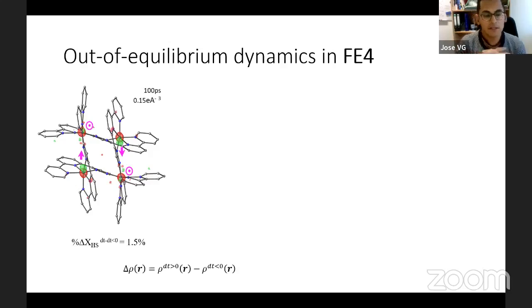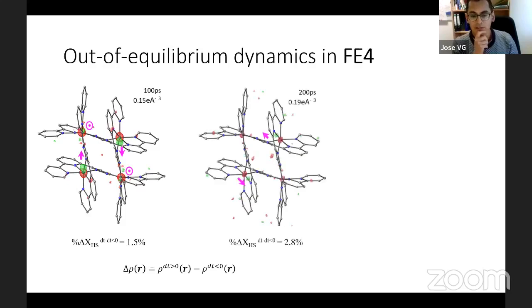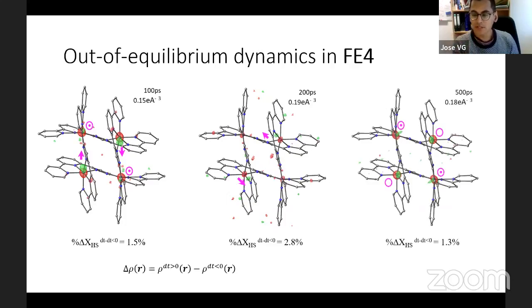And as you can see in the figure, I have put some pink arrows showing more or less how the electron density is changing. For 2 of the ions, the electron density is moving up and down, while the other ones are moving out of and into the plane. So it's moving like this. That occurs at 100 picoseconds, but after 200 picoseconds the movement changed, and this movement continued changing over time, in the first nanoseconds.